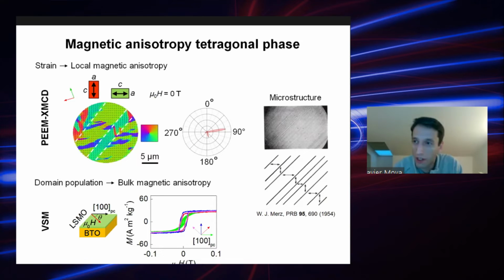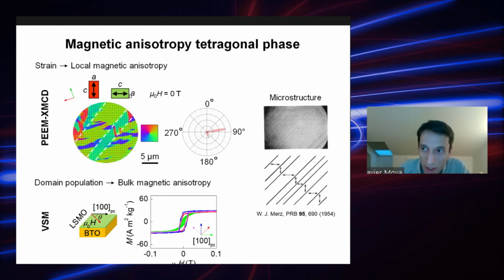So if this is what you expect to see at the surface of the substrate, then let's see how we expect the polarization and the magnetization to look. LSMO has positive magnetostriction, which means that if you apply strain or stress in one direction, the magnetization is going to rotate and align with the direction of the strain. So from that, in this region in this image, where the magnetization is either right or left, we know that this corresponds to a region in the substrate where the polarization is pointing right or left.